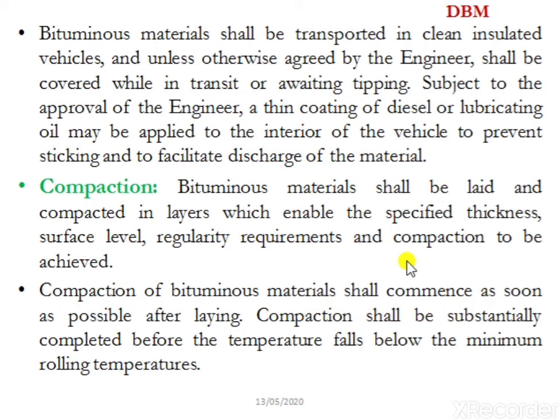The initial or breakdown rolling shall be done with 80 to 100 kN dead weight smooth wheeled rollers. Intermediate rolling shall be done by 8 to 10 tons dead weight or vibratory roller, or with a pneumatic roller of 12 to 15 tons weight having 9 wheels with a tire pressure of at least 5.6 kg per square centimeter. The finish rolling shall be done with 6 to 8 tons smooth wheeled tandem roller, and the number of passes required is to be decided after laying the trial bed.